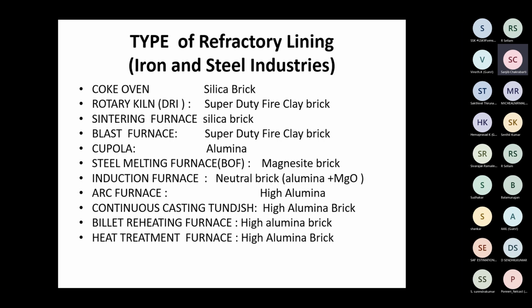Only in a reducing atmosphere can you use it. Arc furnace, High Alumina brick. A very peculiar feature of the arc furnace is that there are arc spots. There are intermittent arcs at high temperature, which cause damage to the inside lining, the arc spots.